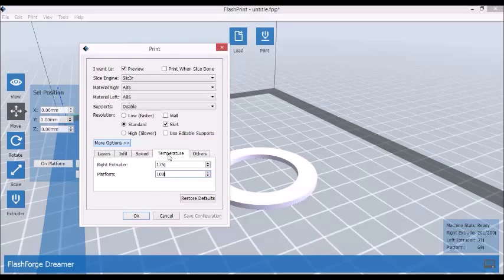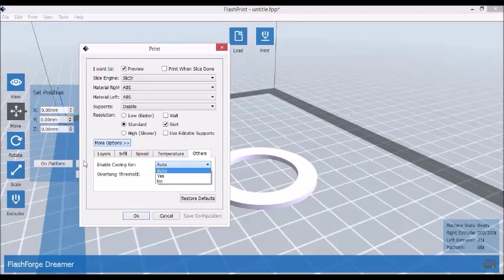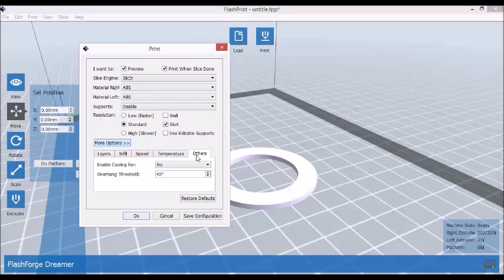Temperature 175 to 200 degrees. I find that FlashForge Dreamer prints well at 175, the extruder temperature. You can try to print at room temperature or lower temperatures, but you might face some sticking issues. So it might not stick properly. I found that at 100 degrees it sticks very nicely and the print doesn't come off, it stays on it. I disable fan cooling and simply allows the adhesion and doesn't solidify it as quickly. That's it for the settings and we'll simply slice it and print it. After it's printed out, we'll have a look at the result.